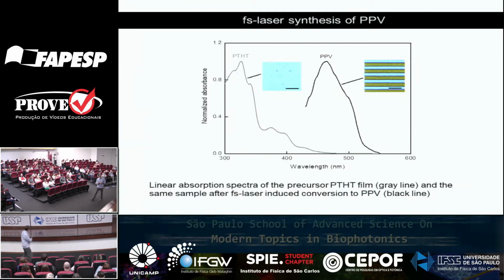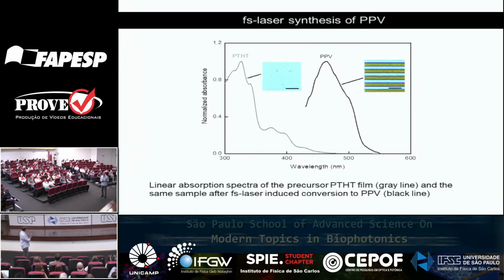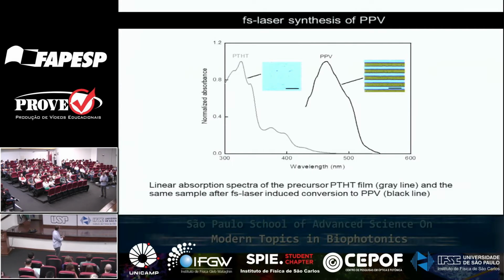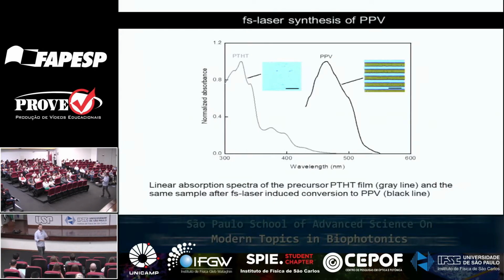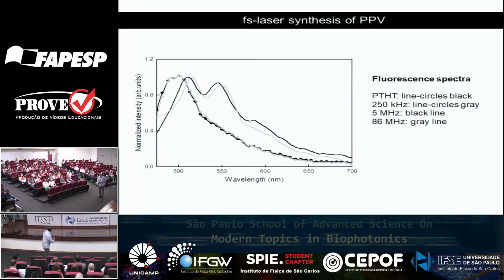So the blue film is actually the precursor polymer. So that's the absorption spectrum of the precursor polymer. And then those are the lines here where I pass the laser beam, of course, in the proper conditions. Of course, we have to choose very well the velocity of the beam, which means the number of pulses, and also the energy in each pulse, and the repetition rate, of course. And then in this case, you see that we have a conversion from the bluish color to the yellowish color, indicating that we are actually promoting the conversion to PPV. So if you measure the absorption spectrum of those yellow lines, that's what you get, which is exactly the expected absorption spectrum of PPV.